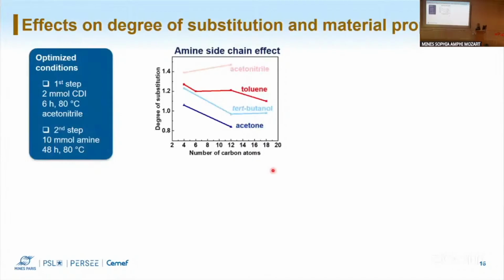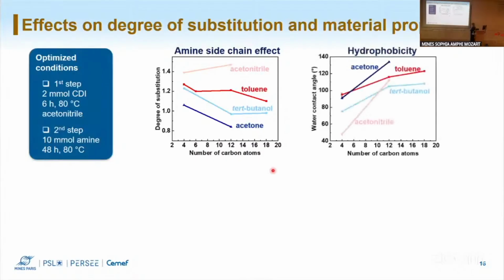And we can see here the effect of the size of the side chain of the amine on the degree of substitution of our materials. And also we can see the different solvents, how they affect the degree of substitution. So in general, we had lower degree of substitution when we were using bigger amines, and we have the highest substitution for acetonitrile. Looking at the hydrophobicity of our final aerogels, we see that even though we had lower substitution with big amines, we had higher hydrophobicity, which makes sense because we have more lipophilic chains in our material.